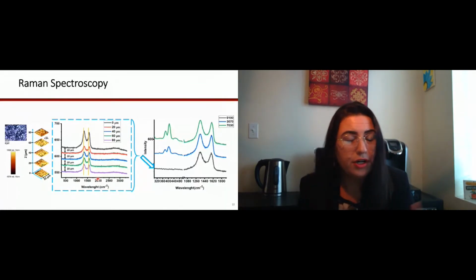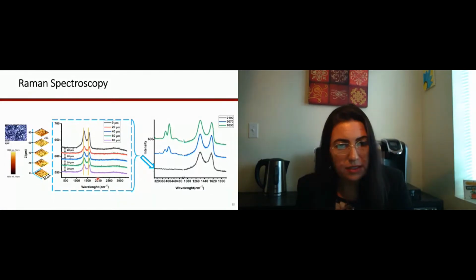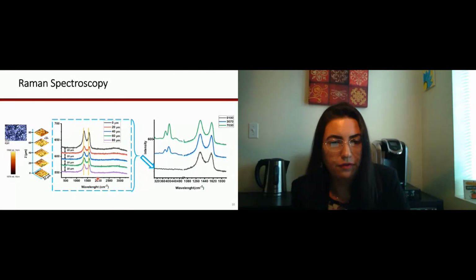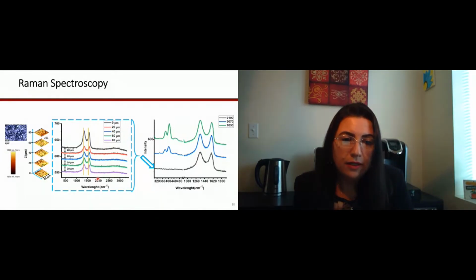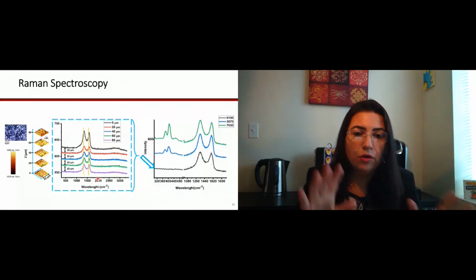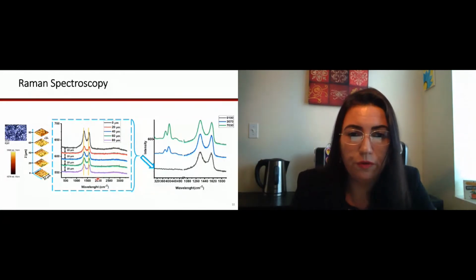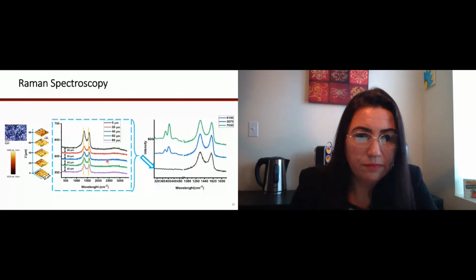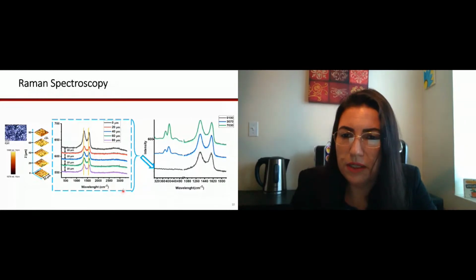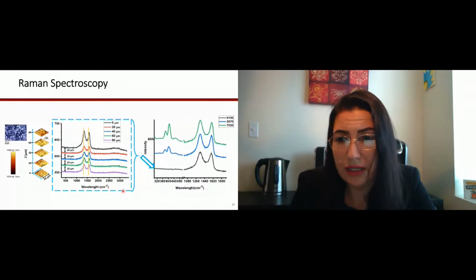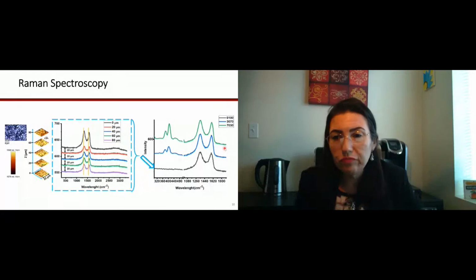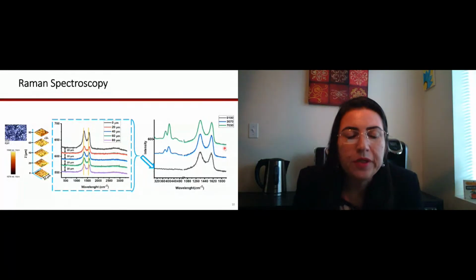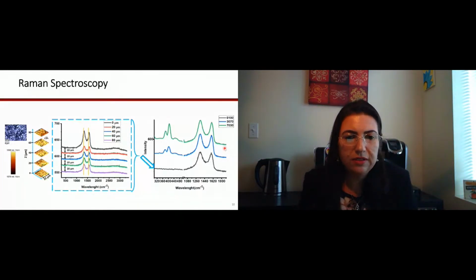I also put it in the oven for reducing. So I had reduced graphene oxide. And after the reduction, we don't have that third peak that you showed before. So as you can see here, those are the peaks of MoS2. And in this case, it shows the peaks of MoS2 and graphene oxide. So why was this study important?